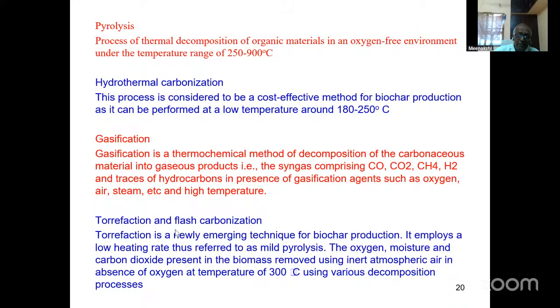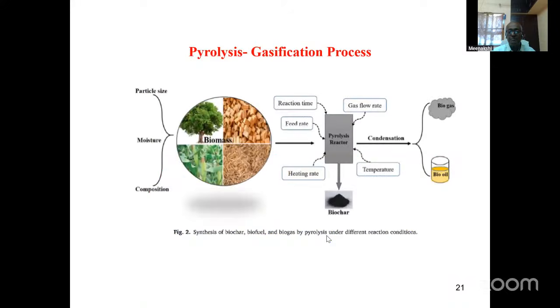And this is a recent process. Torrefaction, or flash carbonization, is a newer technique for biochar production. It employs low heating, referred to as mild pyrolysis, and the oxygen and carbon dioxide present with the biomass are removed using an inert atmosphere, and a low temperature of 300 degrees is used.